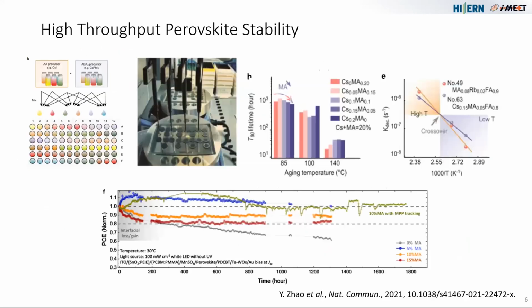From this OPV approach, Zhao was also transferring this to the Perovskite stability approach, like I was mentioning in the beginning. Here we see the Perovskite dropcast films, and after optimizing all these compositions, Zhao could get highly stable Perovskite solar cells. And what he could also find is that in terms of thermal stability, there is a critical temperature where at low temperatures, different compositions are going to be more stable than at high temperatures, which allowed us to get much more insight and also sort of mechanistic understanding, not just high throughput testing, but also finding patterns and finding reasons for why some systems perform better under certain conditions.